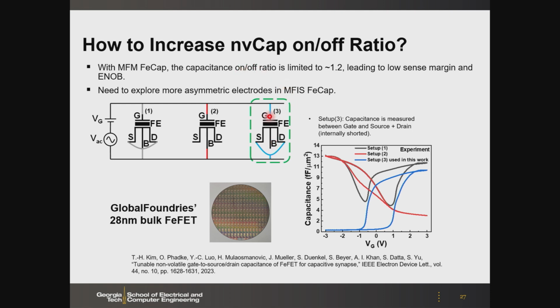So what we did here is to, let's say, measure the CGS and CGD where the S and D is connected. So the key is that we cannot connect the body together. If we connect the body together, then this is like a normal setup. So here we have to use another terminal to ground the body. Okay. So if we do that, then this is a CV curve. The blue one, you will see that here we create a very large window at 0 voltage. So this window is larger than 20, I believe.